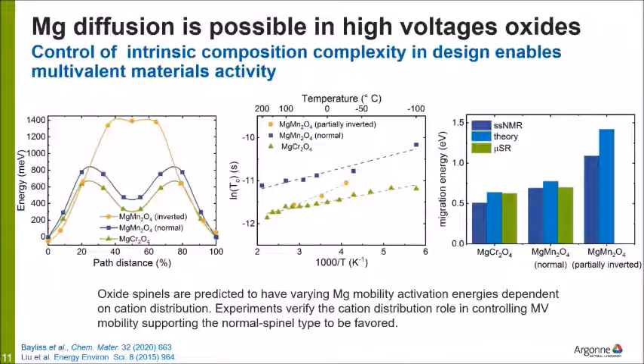And you can see that inverted spinels have very high activation energy, low mobility. And as we move towards the normal, that seems to benefit magnesium diffusion from tetrahedral to tetrahedral site, which is consistent with expectations. And then we can see that by changing the B site cation from manganese to chromium, we can further lower the activation barrier.